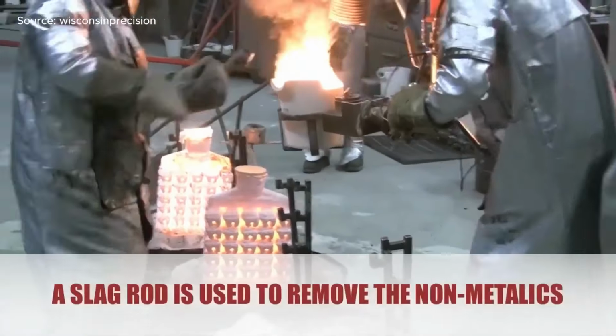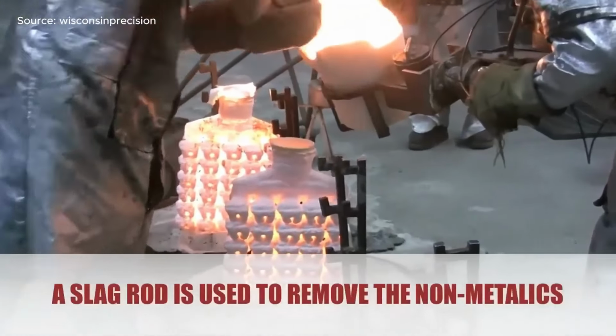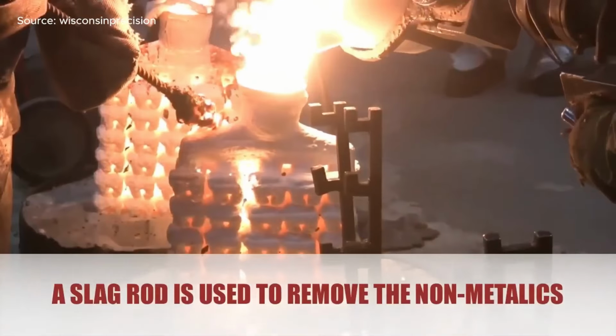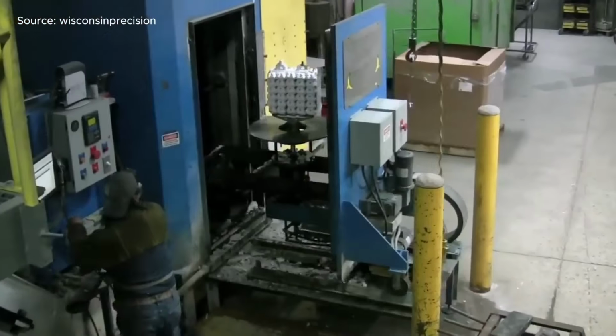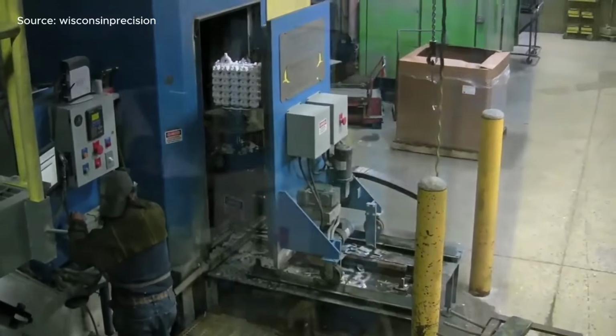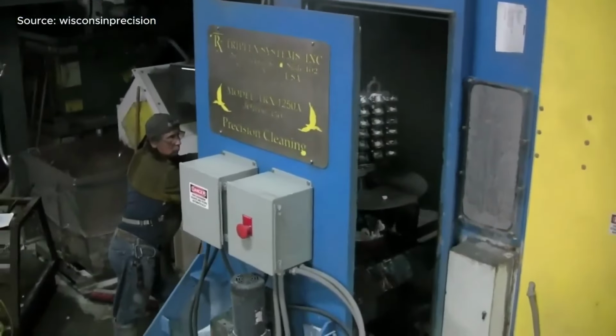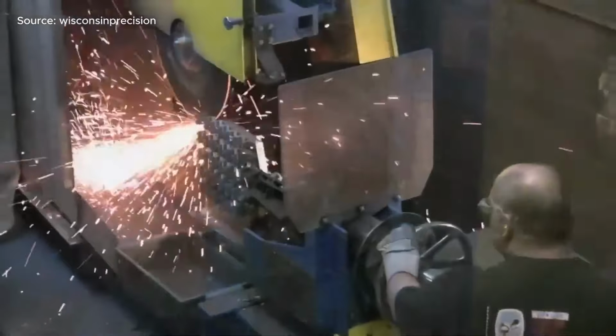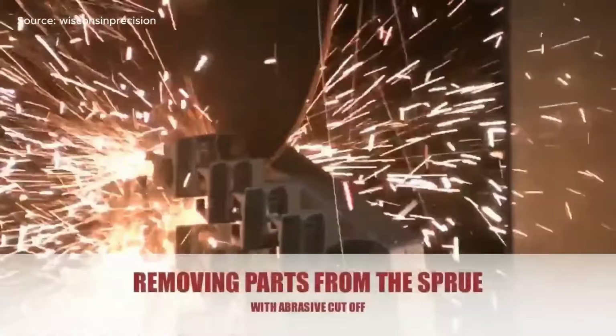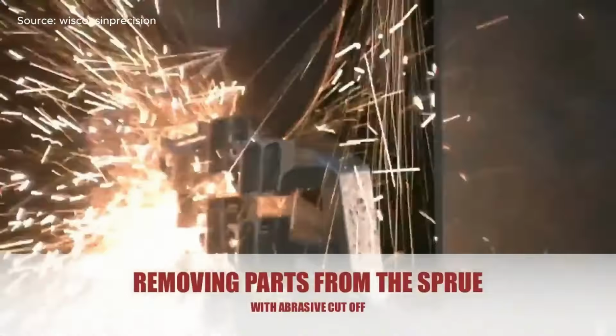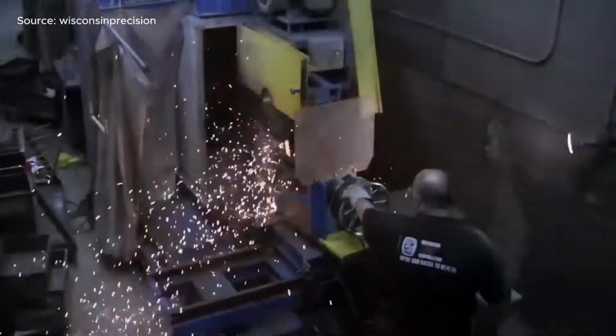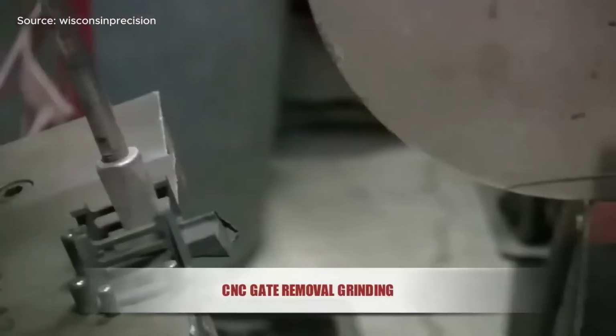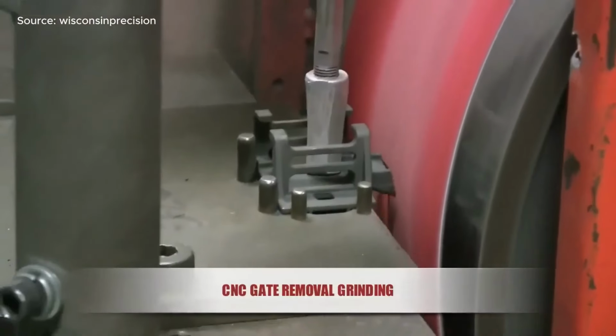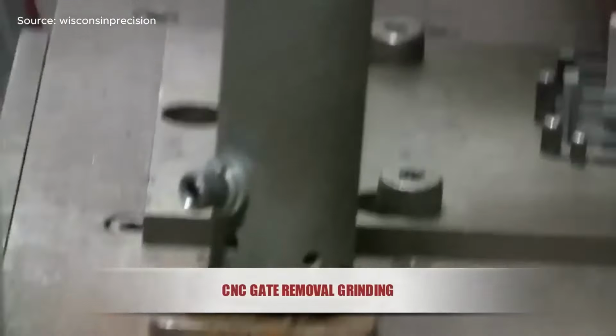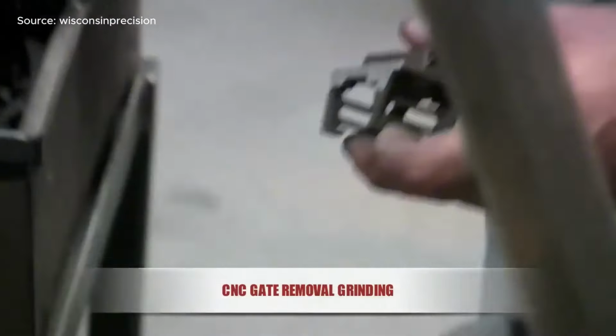Metal melting and pouring. 304 stainless steel is induction melted at 3,000 degrees Fahrenheit and poured into the preheated ceramic molds. A slag rod is used to remove non-metallic impurities from the molten metal before pouring to ensure material purity. Casting, removal, and finishing. Once the metal has solidified, the ceramic shell is broken away, and individual cast parts are removed from the sprue using an abrasive cutoff process. Further refinements, such as CNC grinding, are performed to remove gates and improve dimensional accuracy.